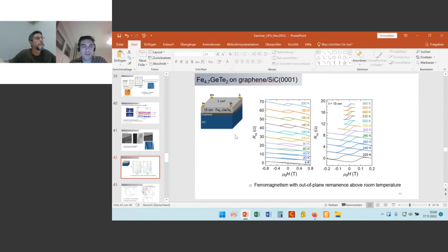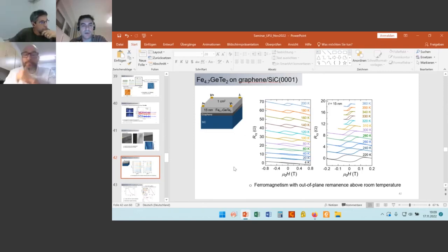We grew this size, and we actually perform magnetotransport on these very large sizes. In principle, we also grew, I do not show here, but this FGT can also be grown on sapphire wafers, and then we grow 2-inch wafers, and they are very uniform.